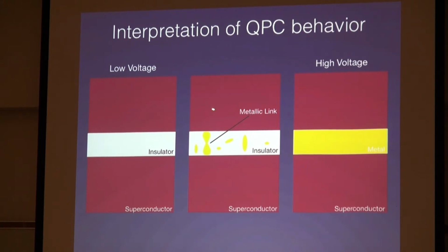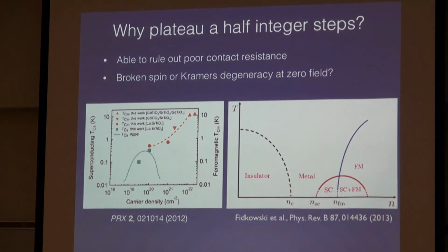So as you turn up the electron density, what's going to happen first is you won't get a direct transition to the metallic state. Actually, puddles of electrons will start to form that kind of are confined to the disorder potential. And in a few devices, not all devices, we see that as these puddles grow larger, there's a point when two of the bigger puddles, or three bigger puddles, connect, and you have this very small constriction. And so we think this small accidental constriction is what's giving rise to the quantum point contact behavior. It's something that we can and in the future will control, but for now, in some devices we get what looks like one connection. In some devices, we actually get what looks like two connections. You can see sort of two parallel quantum point contact-like behavior. So, okay, that's probably why we're seeing these plateaus in conductance.